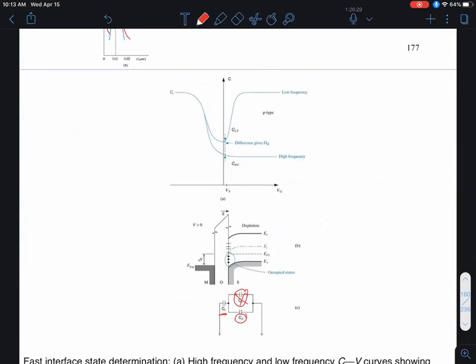And therefore now, compared to the scenario where there were no interface charges, if I have interface trap charges, the overall capacitance measured here would be larger because these 2 add up. But that will add up and respond only if I do the measurements at low frequencies applied to the gate voltage. If I vary the gate voltage relatively slowly, so that these interface charges can respond to that. On the other hand, if I vary it at a high frequency, even these fast interface trap charges can't keep up with that. Therefore, for all practical purposes, you can kind of ignore this.